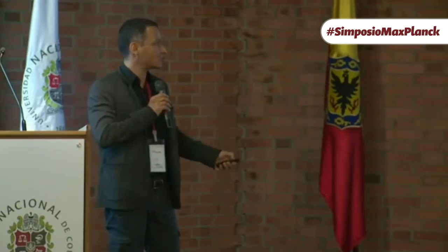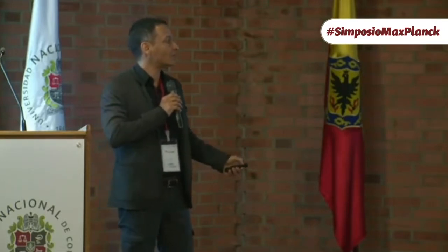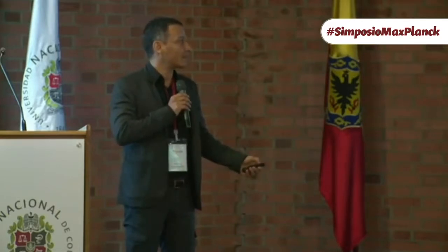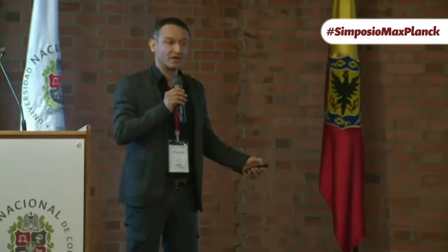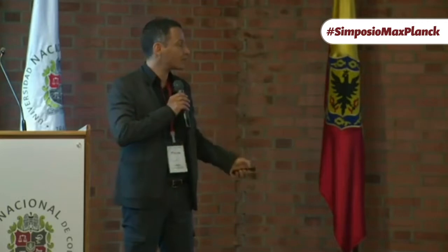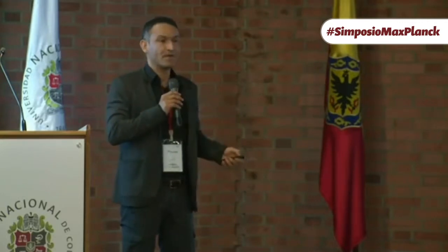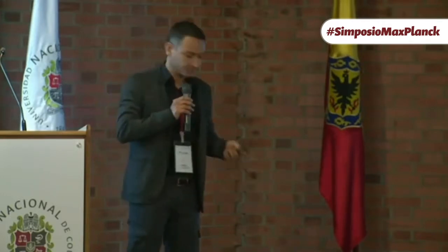And in this chronoamperometry, you can see better how the current intensity is higher compared with the carbon nanotubes decorated with iron and covered with graphene. It means the graphene layer is decreasing the current intensity a little bit, but it is helping us to have a stable hybrid for even 1 month.